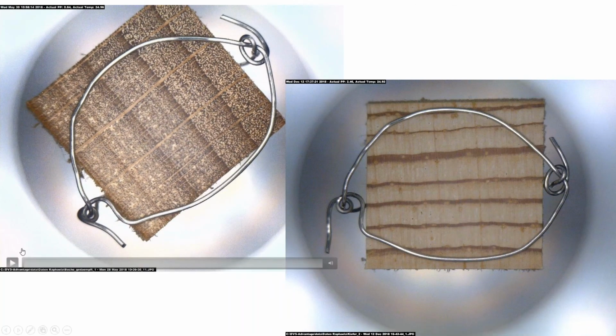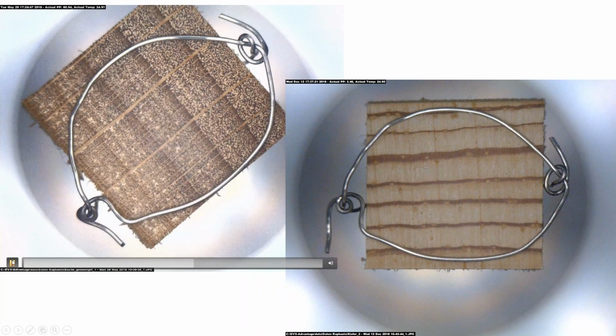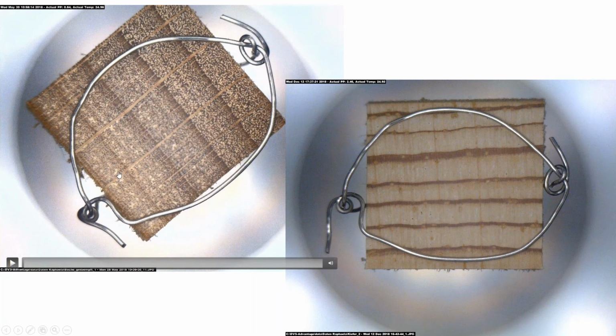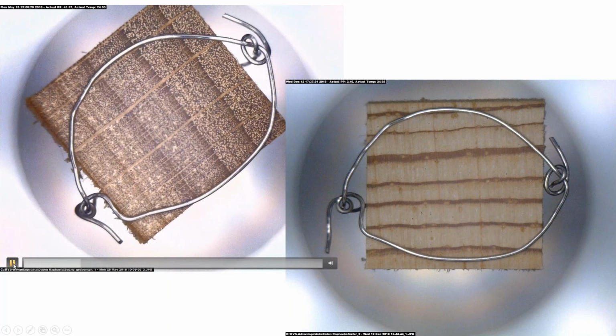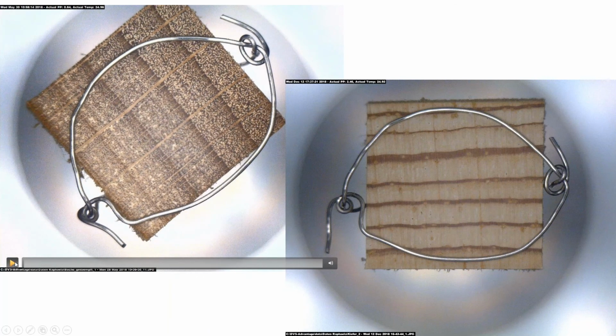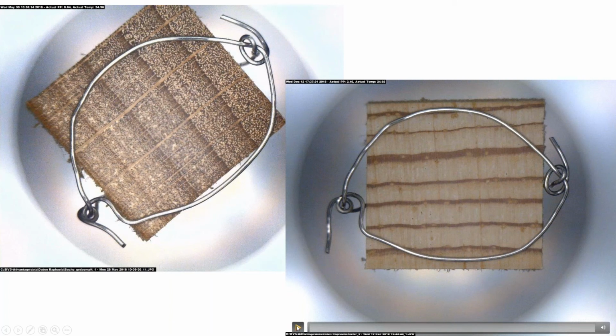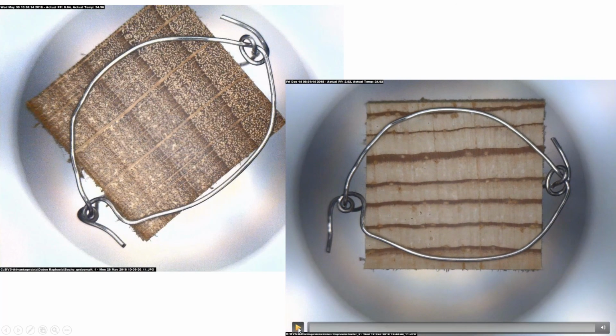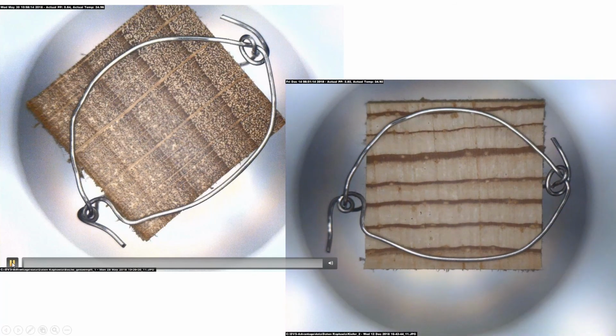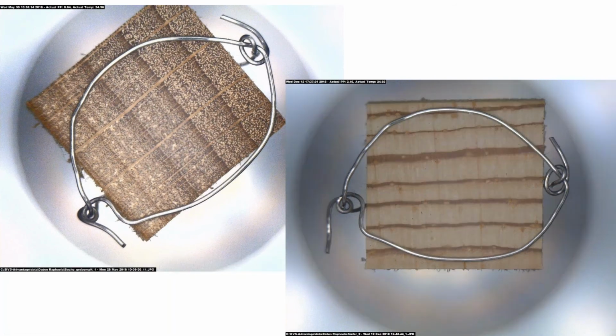So when we do all the pictures, like these are 11 pictures that you're looking at, I think, or 8 pictures. This is the beech. This is a steamed beech, by the way. You see a little bit of the brownish color. This is a nice teaching tool, actually, this videos tool for the students, because you see tangential radial swelling and shrinking could be demonstrated nicely, and you could see that tangentially it's really twice the radial. So these are little side products that are quite handy, which could be produced with the advantage that we have.